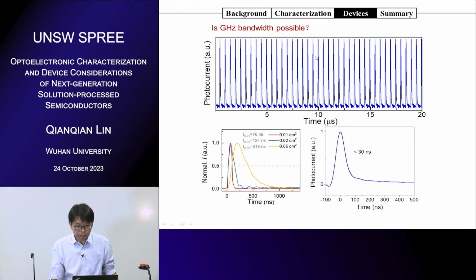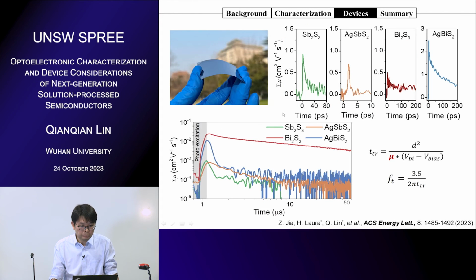And recently we reached around 20 nanosecond response. It's very fast. It's based on perovskites, and we also want to push it to over gigahertz. So that is our aim, because from the charge transport, it does not have any problem. It has very high mobility. It should have very fast charge transport, and the devices should respond faster, but for real devices, we cannot get higher. It's mainly dependent on the device structure.